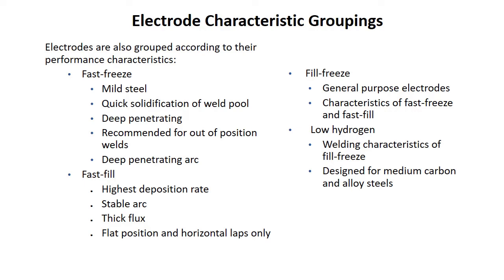Electrode characteristic groupings. Electrodes are also grouped according to their performance characteristics. So we would have like a fast freeze. A fast freeze would be something like a 6010. It would be a mild steel, quick solidification of the weld pool, deep penetrating. If you've ever welded with 6010, it's got a really deep penetrating digging type arc. It's recommended for out of position welds.